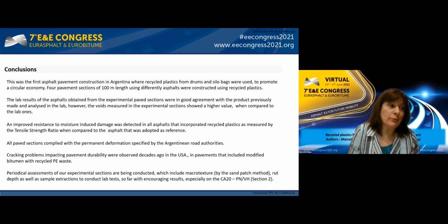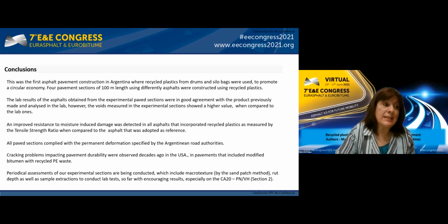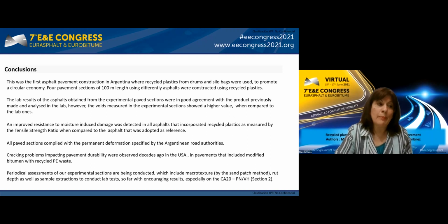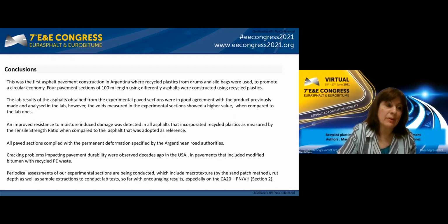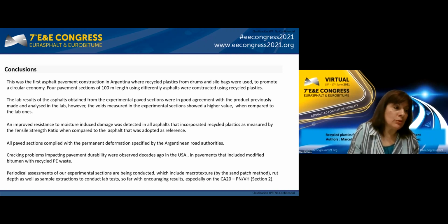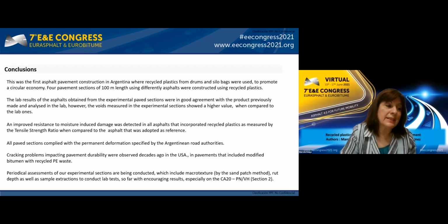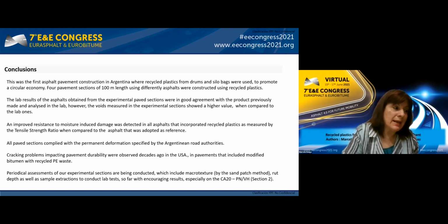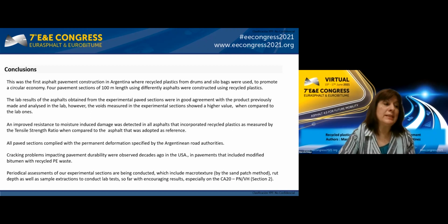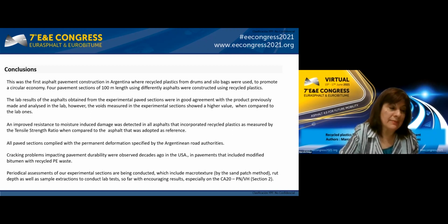The following conclusions were obtained. Firstly, the lab results of the asphalt obtained from the experimental paved sections were in good agreement with the product previously made and analyzed in the lab. However, the voids measured in samples extracted from the experimental sections showed a higher value when compared to the lab mix. Secondly, an improved resistance to moisture damage was detected in all asphalt that incorporated recycled plastic, as measured by the tensile strength ratio, when compared to the CA asphalt adopted as reference.